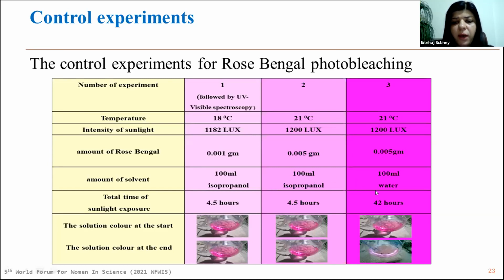Increasing the amount, here we change the solvent. In experiments number 1 and 2, we used isopropanol as a solvent because it is a part of the photoreduction of benzophenone to prepare benzopinacol. We change it to water. After 42 hours, we see the change in color of the solution from pink to pale pink.